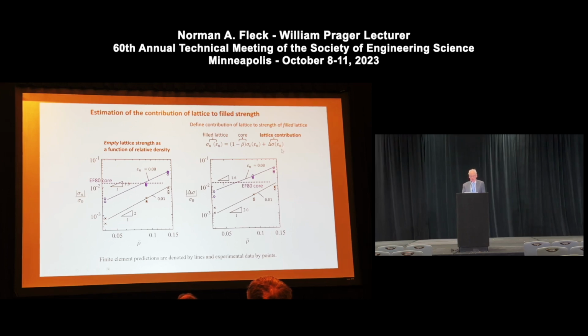And when we do so, we can get a plot of that against relative density, and we can compare that plot with the stress-strain curve just for the empty lattice. And thereby we can ask the question, does the core, the incompressible core, actually change the effective strength of the lattice? And the answer is not by very much, a little bit. So at a strain level of 8%, a bit above the yield value, here is the empty lattice response. I'm plotting stress against relative density. And on the right-hand side, I'm plotting the contribution to the macroscopic response of the filled lattice due to the lattice itself.